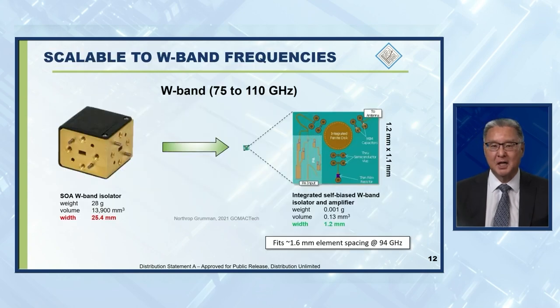The new technology doesn't stop at 40 gigahertz, but it's scalable to frequencies as high as W band in the 75 to 110 gigahertz range. The photo on the left is a state-of-the-art waveguide isolator in W band. To the right, and to scale, is a self-biased hexaferrite isolator integrated with a W-band amplifier. The whole package weighs about 1/1000th of a gram, and the 1.2 millimeter by 1.1 millimeter form factor is compatible with the half-wavelength spacing at 94 gigahertz. These newly developed self-biased hexaferrite materials have opened up a wide range of commercial and defense applications, from arrays for 5G communication to AESA radar systems.